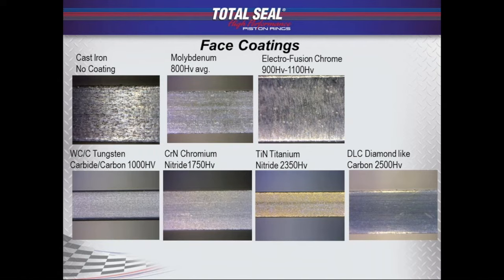Next one's chromium nitride. Very, very common coating today, very popular. About the middle of the scale as far as hardness goes on PVD type coatings, about 1,700 Vickers. Little higher coefficient of friction. I think off the top of my head, it's about a 0.4. Wears very well. Common coating to see put on stainless valve stems. And then you work your way up the scale into the titanium. Titanium nitride, about 2,400. Harder coating, gonna last longer. Similar coefficient of friction to the chrome nitride, but it's gonna take a little bit longer to seat up. It is a harder coating, but wears better.